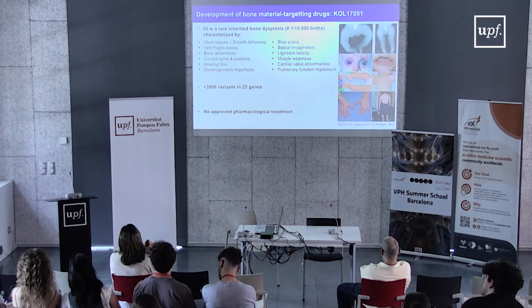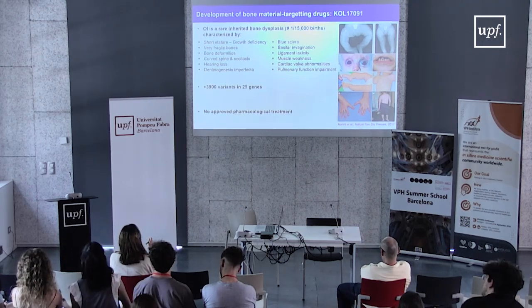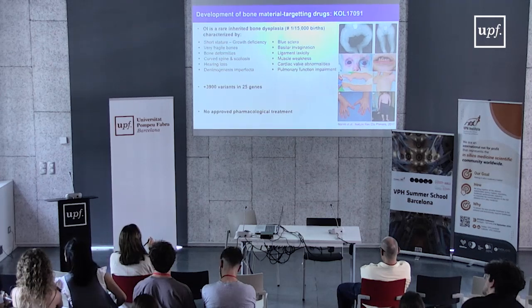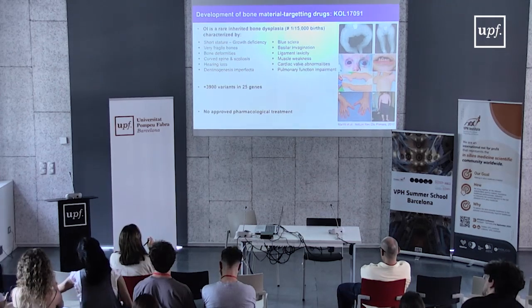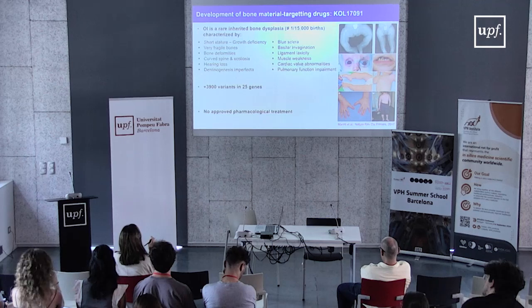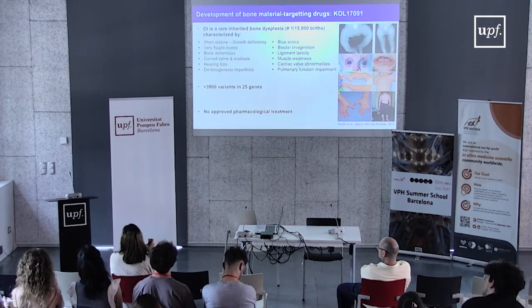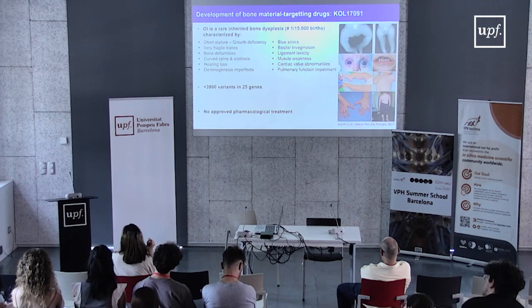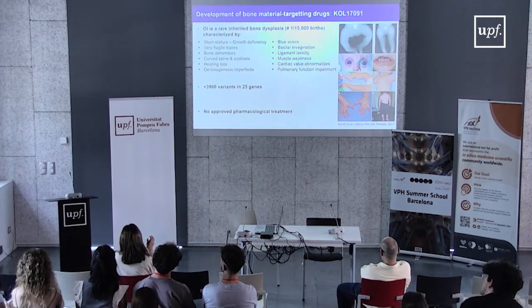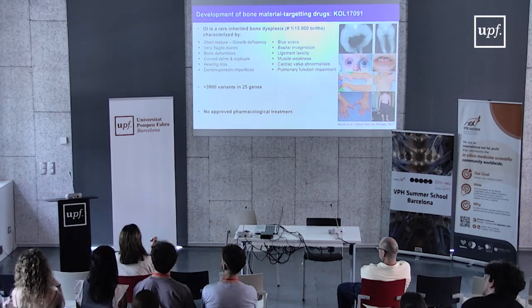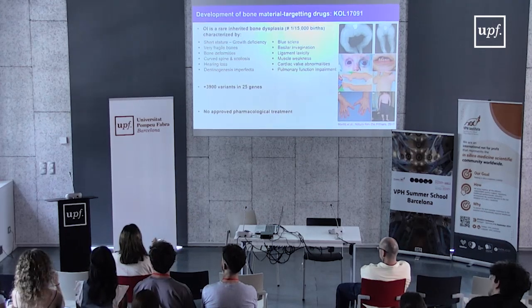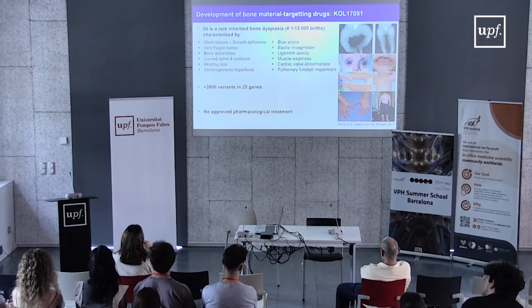And there were some clinical trials using bisphosphonate in OI, showing that bisphosphonate can increase the bone mineral density, the amount of bone, which is normal because it's the job of a bisphosphonate, but with no sign of reduction in the number of fractures that the children could have. And even more dramatic, the children who were treated at an early age with bisphosphonate were more prone to develop fractures in adulthood than children treated with a placebo.